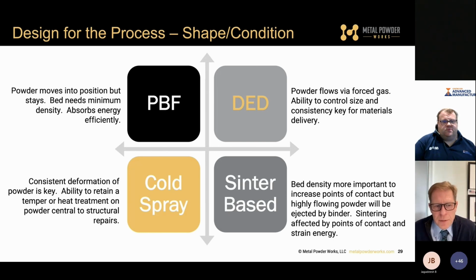On the cold spray side of things, what you're really interested in is consistent deformation behavior by the powder. And so our ability to retain a temper or heat treatment on the powder would be central to being able to certify a structural repair. Certifying a structural repair in an atomized powder that hasn't been heat treated is difficult, because that aluminum, for example, will just continuously age at room temperature. So your performance is then changing, week by week.